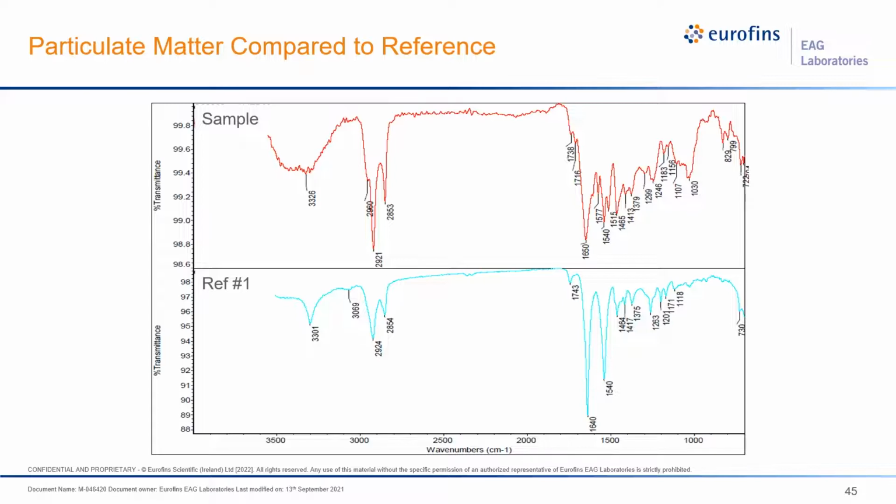Also, the polyamide reference material has two sharp bands that are more intense than what's in the sample. There are a couple of reasons that could contribute to this. First, they're not a good match; they're not exactly the same. Second, the sample itself may be a mixture of something other than just polyamide. Some other contamination could lead to this spiky splitting of the peak, or shouldering.